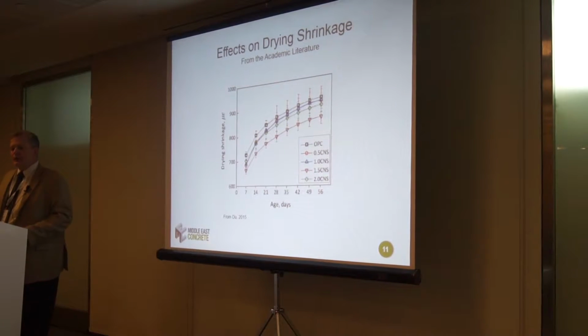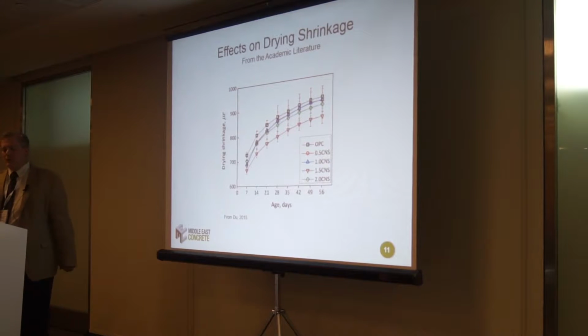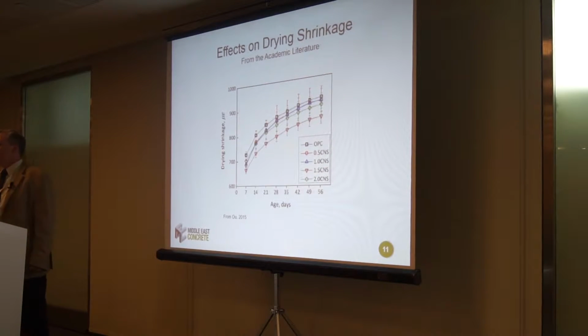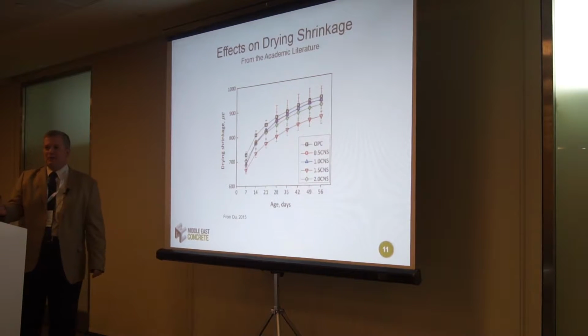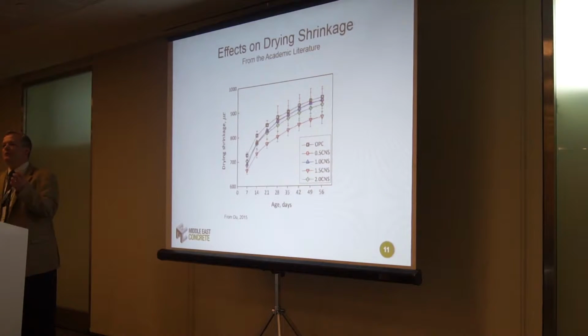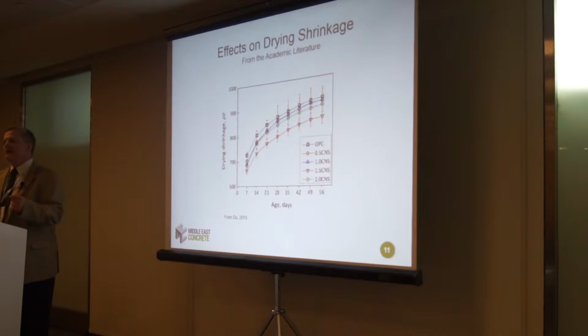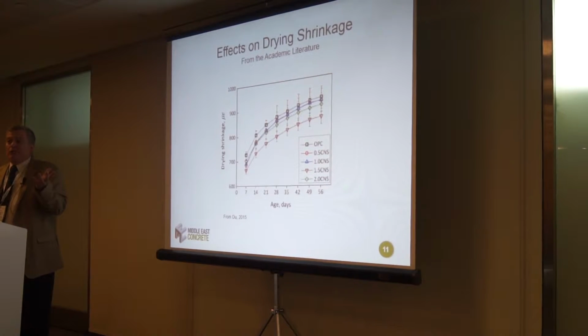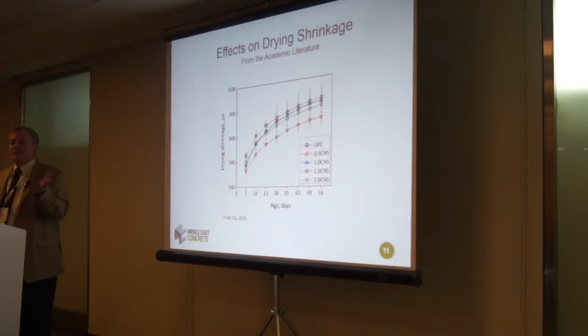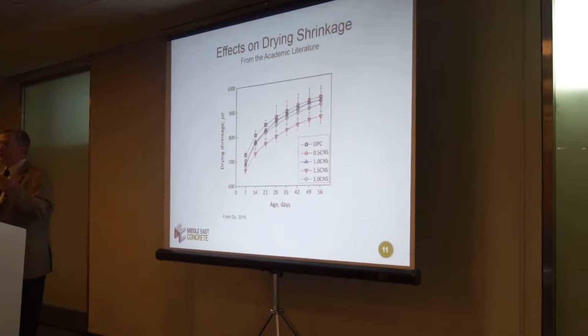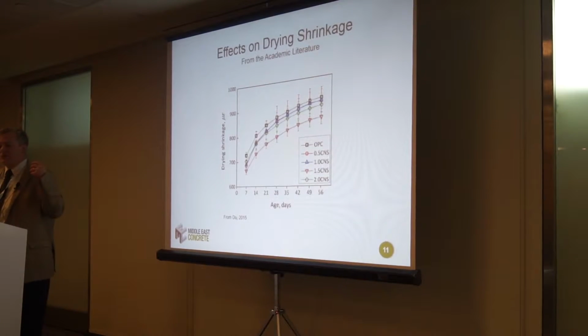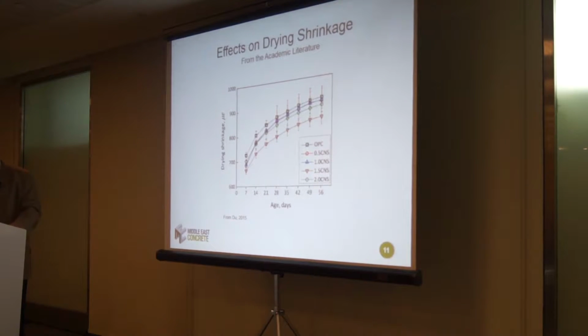I want to switch to effects on drying shrinkage, and you may be saying to yourself, wait a minute. Okay, so it affects compressive strength. We get an increase in compressive strength, and now you're going to tell us that it also does something with drying shrinkage. Well, yeah, because remember, the only really effect that the colloidal nanosilica is having is it's filling pore space. And filling pore space, a lot of good things happen when you close that pore space. So drying shrinkage, we know from the academic literature that colloidal nanosilica reduces drying shrinkage by quite a bit.